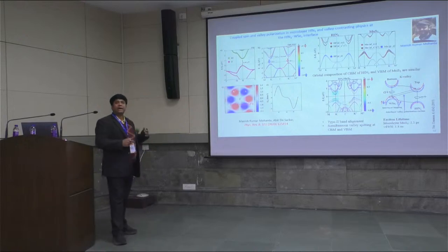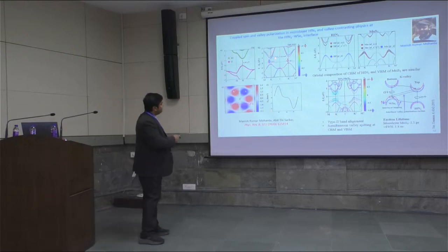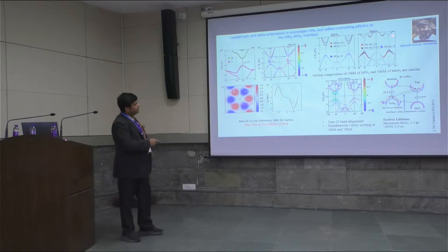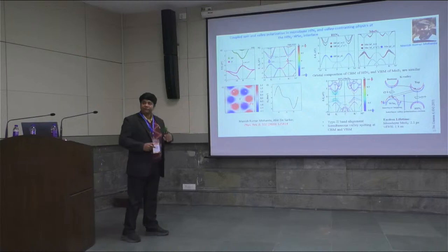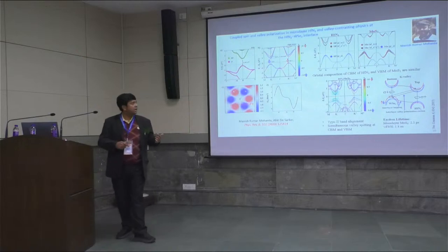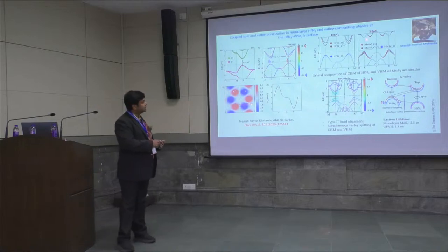but we have explored the valleytronic properties in this material. It shows a large Zeeman type valley spin splitting at the conduction band edge, which is complementary to that of MoS2. It shows a large splitting at the valence band. Now, if you replace sulfur by a heavier element, that is tellurium, the spin orbit coupling will be higher, and as a result the splitting will also be higher in this case.